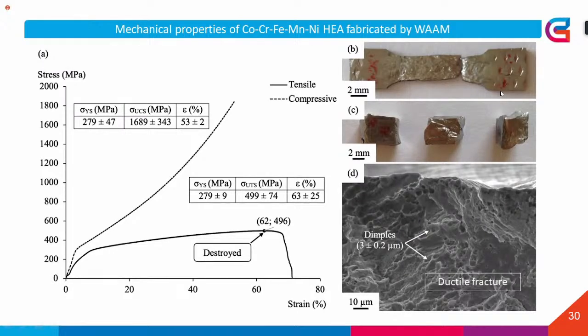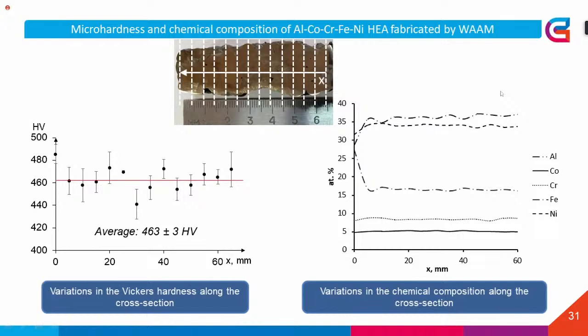The analysis of the second alloy showed us that the mechanical properties are also at a good level. The results are shown here. We have analyzed, as well, the micro hardness along the cross section. So the analysis was done along the whole block. You can see that micro hardness is not highly changed, so it goes quite equally. Nevertheless, the composition plays an essential role. So we can see different numbers here.